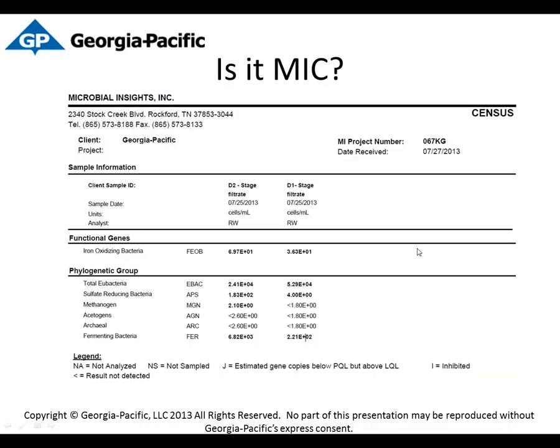So we sent samples to Microbial Insights, and it came back, yes, we do have MIC. We didn't get the concentrations we expected, but we did have a presence of it, especially the fermenting bacteria. The sulfate-reducing bacteria was relatively low. And that's what everyone was telling us, is if we do have MIC, it had to be a sulfate-reducing or sulfur-oxidizing bacteria. We found those concentrations relatively low.